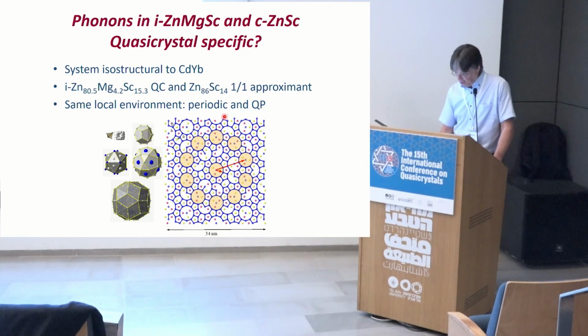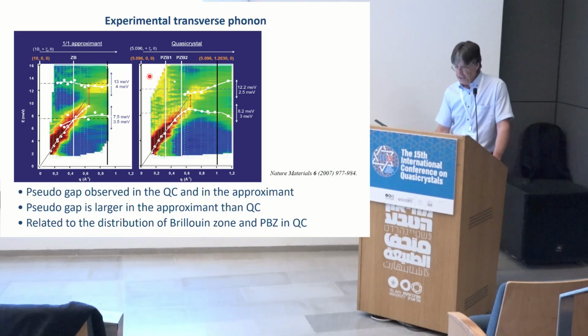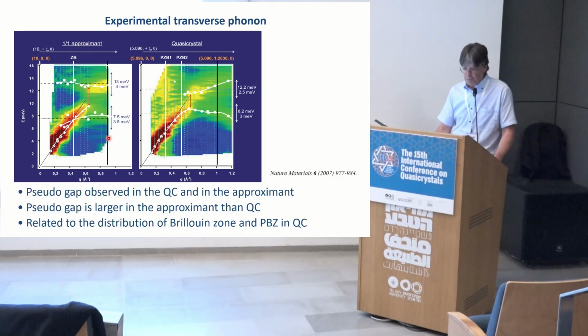We did compare that to the zinc-magnesium-scandium quasicrystals, where we have both the 1-1 approximant and the quasicrystal, which is shown here. And what is shown here is what is observed in the 1-1 approximant. We have a single zone boundary and a well-defined pseudo gap opening here. Whereas here, because we have two pseudo-zone boundaries, we have a smaller gap opening.